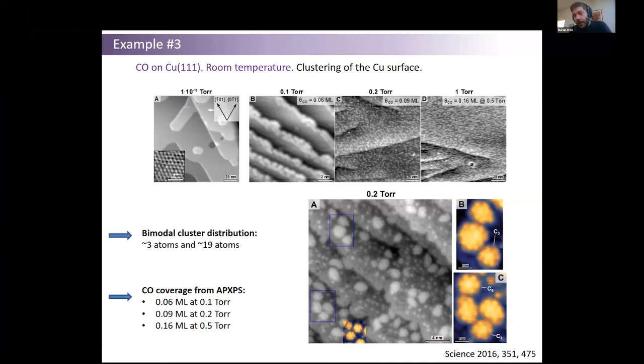And the reason is, of course, you can explain this with energetics. The formation of these clusters costs some energy. But after we form these clusters, the carbon monoxide adsorption energy will be significantly higher on the newly formed edges compared to the flat terraces, so that the total energy gain through adsorption of carbon monoxide on the edge sites is going to be more than the formation energy of the clusters.